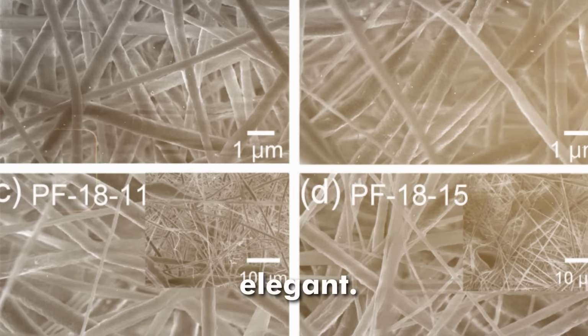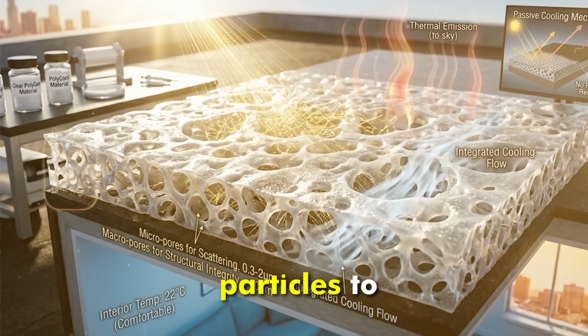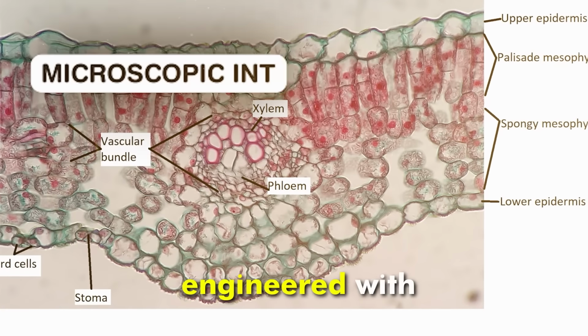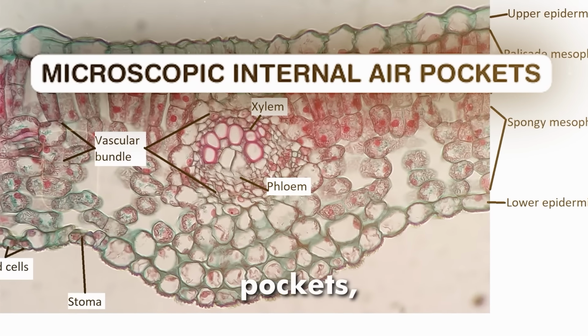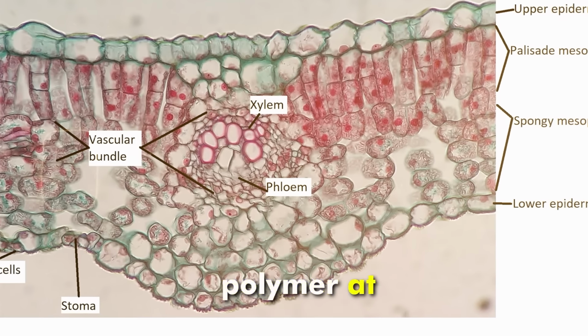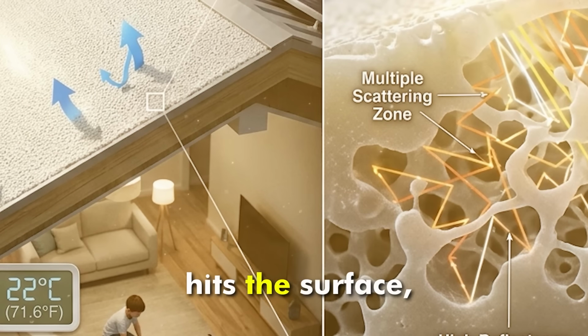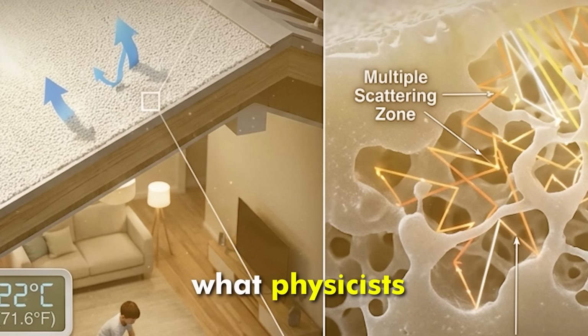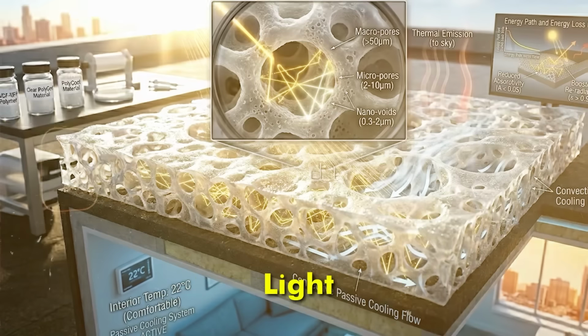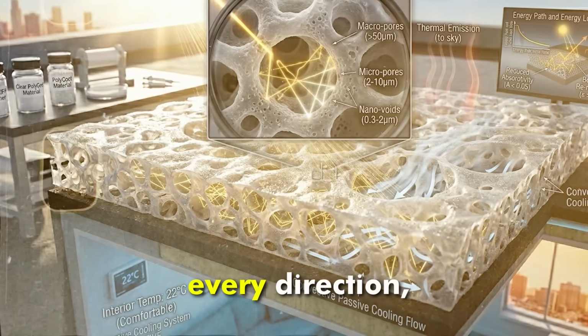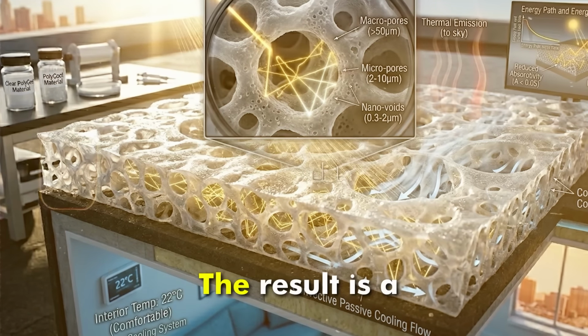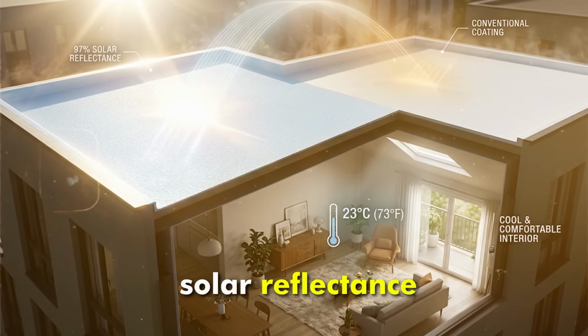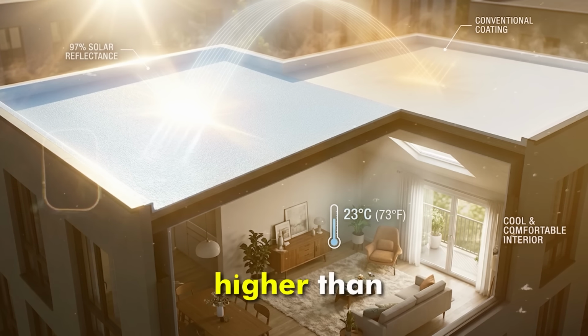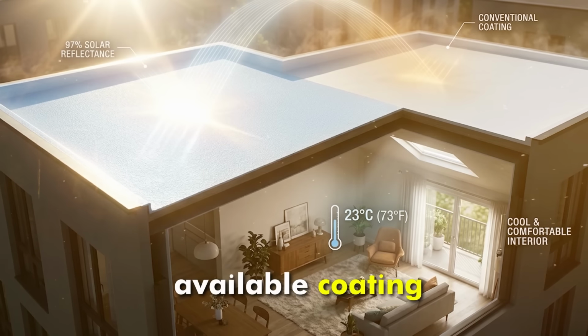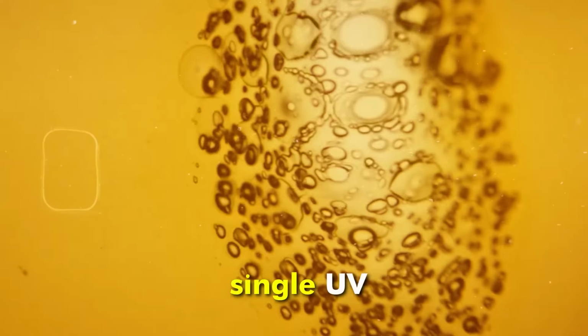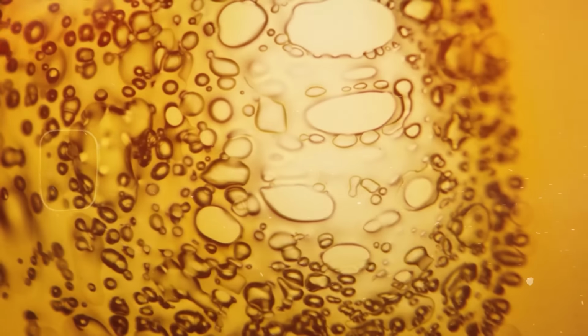The mechanism is elegant. Instead of using white pigment particles to scatter light, this material is engineered with microscopic internal air pockets, pores distributed throughout the polymer at precise scales. When sunlight hits the surface, those pores cause what physicists call multiple scattering. Light bounces through the interior of the material in every direction, losing energy before it can be absorbed. The result is a solar reflectance that approaches 97%, higher than almost any commercially available coating on the market today, without a single UV-absorbing chemical in the formula.